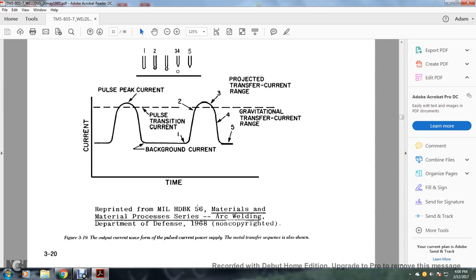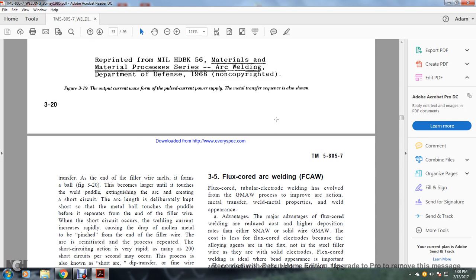Figure 319 shows the output current wave form of a pulse current power supply with the metal transfer sequence as shown. You have your current versus time, where the current runs with a pulse, from peak current down to a background current, with pulse transition currents 1, 2, 3, 4, and 5. Above the line, at your pulse peak current, you have a projected transfer current range. At your bottom background current, you have a gravitational transfer current range.